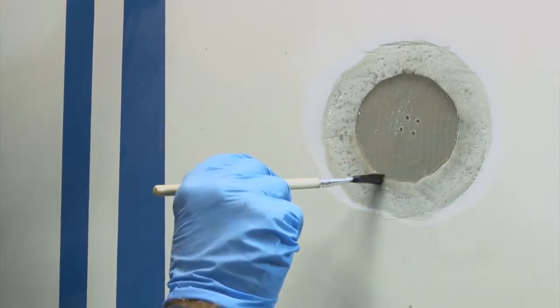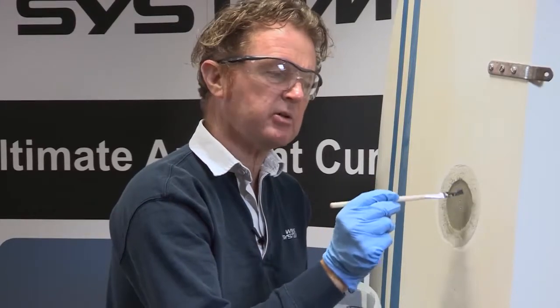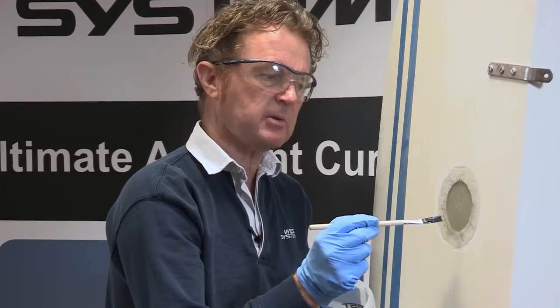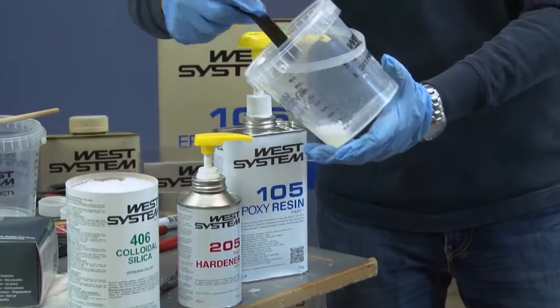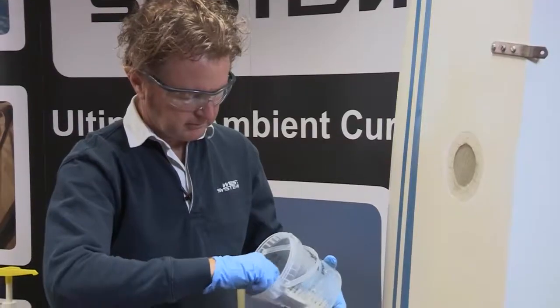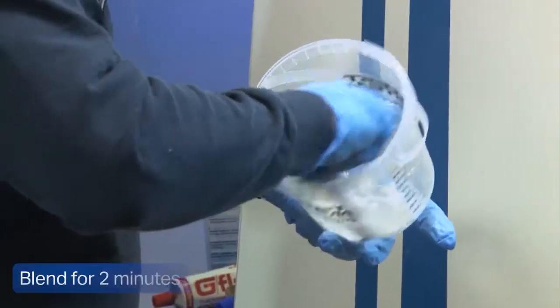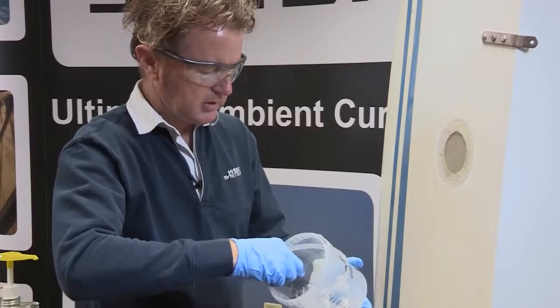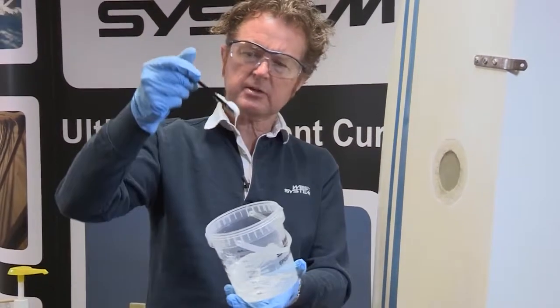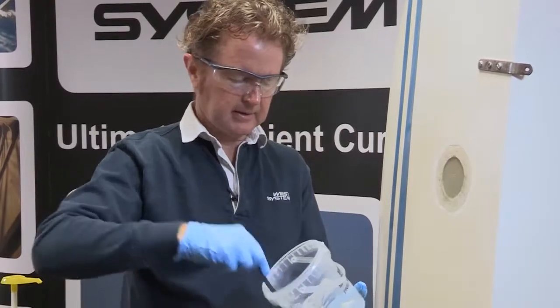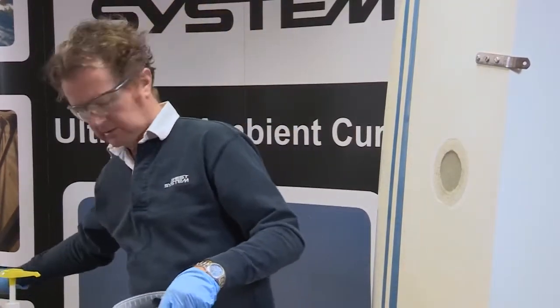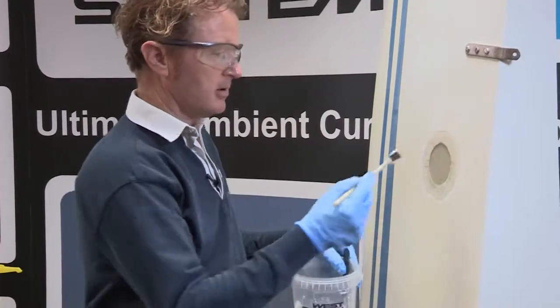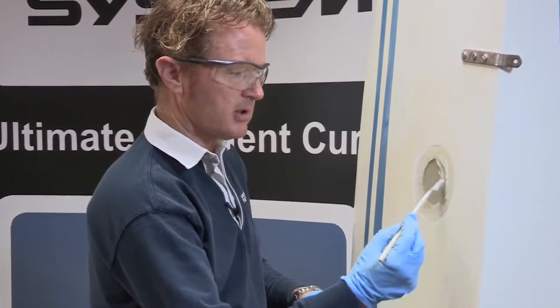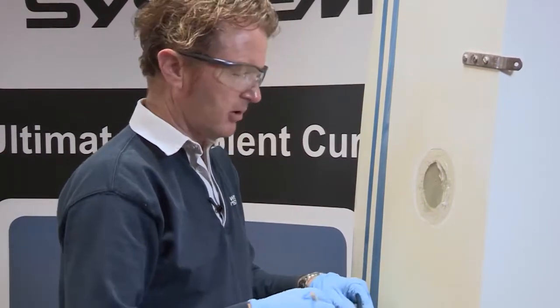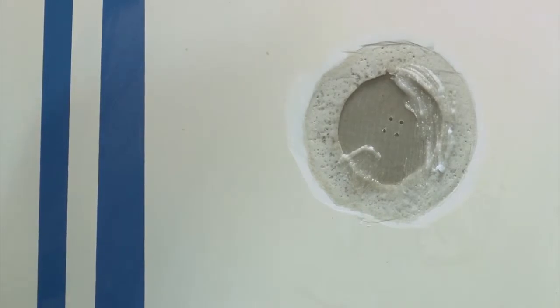I'm now going to make a slightly thicker mix to just fill this discrepancy around here so that we don't get an air bubble or an air gap here that compromises the strength of our repair. I've just added some West System 406 colloidal silica to the epoxy mix. See, I've now got quite a creamy consistency. And I can use my brush to brush that carefully into place to bridge that discrepancy between the backing plate and our bevel.